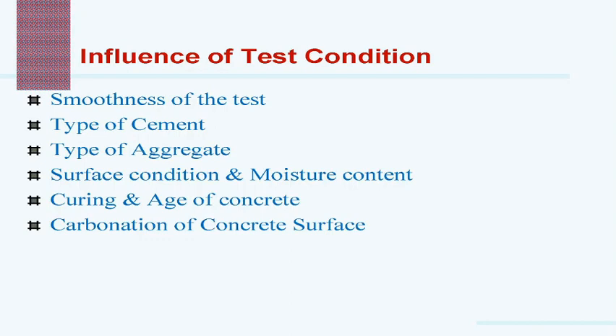The rebound number method is suitable only for closed texture concrete. Open texture concrete, typically of masonry block, honeycombed concrete, or no-fines concrete, are unsuitable for this type. All correlations assume full compaction, as the strength of partially compacted concrete bears no unique relationship to the rebound number. Troweled or floated surfaces are harder than molded surfaces and tend to overestimate the strength of concrete. A wet surface will give rise to underestimation of the strength of concrete calibrated under dry condition. In structural concrete, this can be about 20% lower than in equivalent dry concrete.